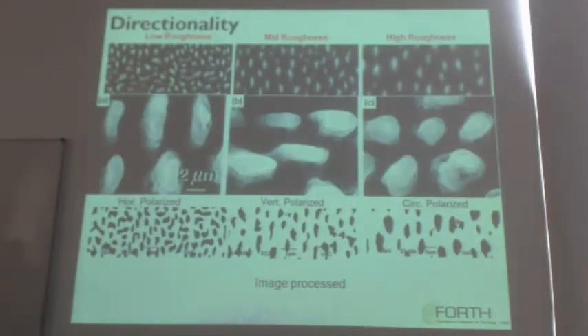Yes, this is an interesting effect of laser-material interaction. It starts from a sinusoidal modulation of the melt. The material is melted with the interaction of the laser pulses. You have one pass, so you have melting, and then you have a sinusoidal modulation of the melt, because it is governed by the modulation of the electric field, on the surface of the material. So the surface is melted.